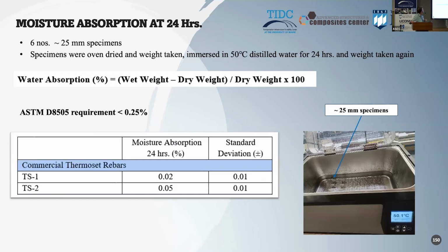Next one. Now, moisture absorption. This is a key property. The standard says no more than 0.25%, okay? And there are the conditions that are given there in 24 hours. And we have done this, and what we measure is a very, very small percentage of moisture absorption for both systems, meaning the polymers that are used there are behaving as expected.